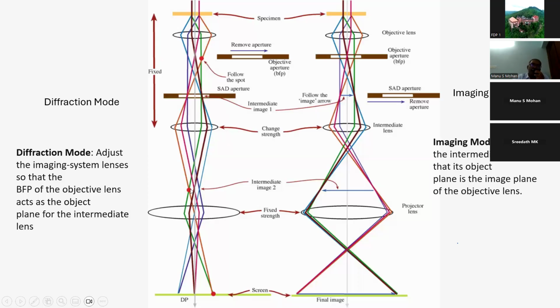So now you change the strength, you reduce the strength. The spots you see here, those three spots, will be further away from the specimen, and then those three spots you are focusing, that is the diffraction pattern.